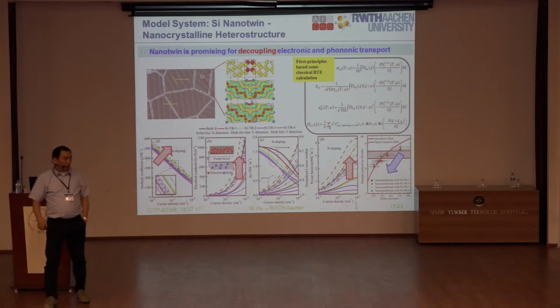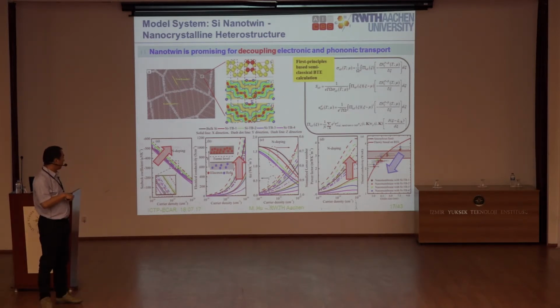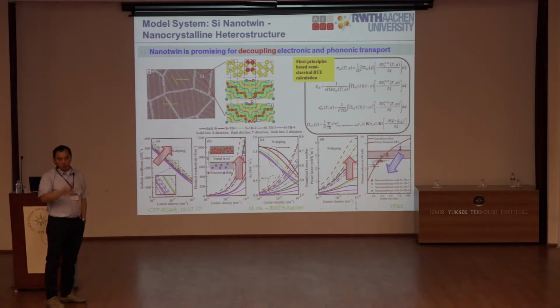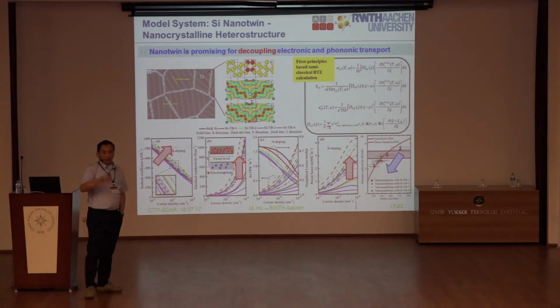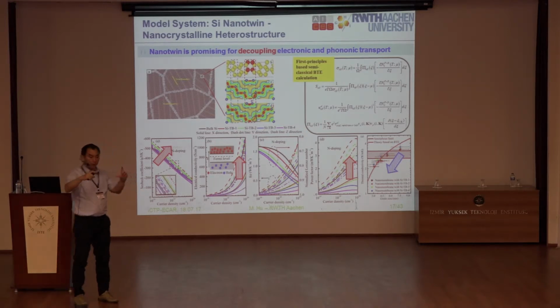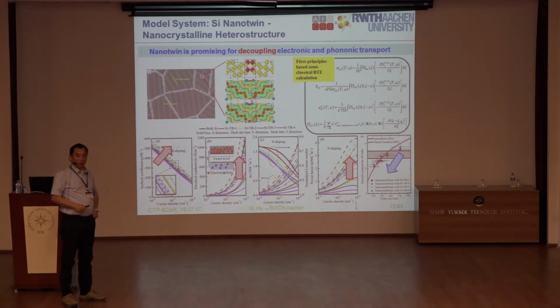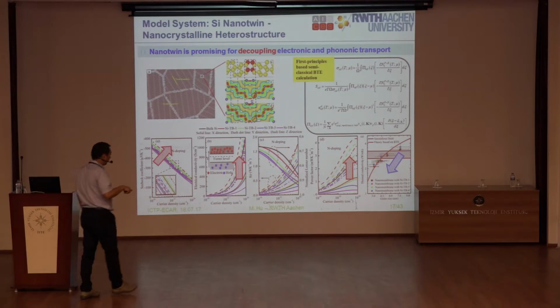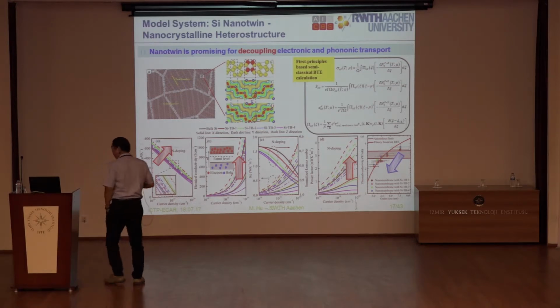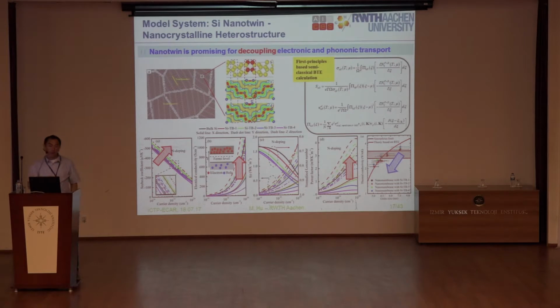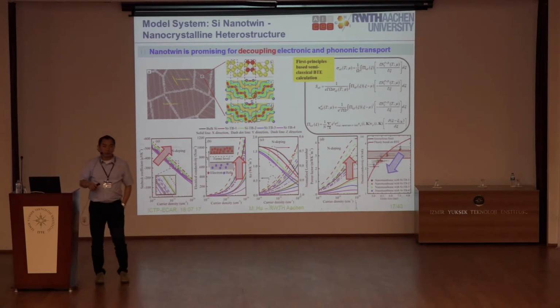We take the value from some literature, where they just measured silicon. So we didn't consider the boundary effect in the measured value. We just use some simple model to take a look at the boundary effect. The value that you pick is a constant value. Yeah, it's a constant value. So we take it from the bulk, and then we consider this boundary effect and also the twin boundary effect by some mathematical model. And then we finally calculate the power factor. The phonon part is by classical MD. Yeah. Do you have questions?